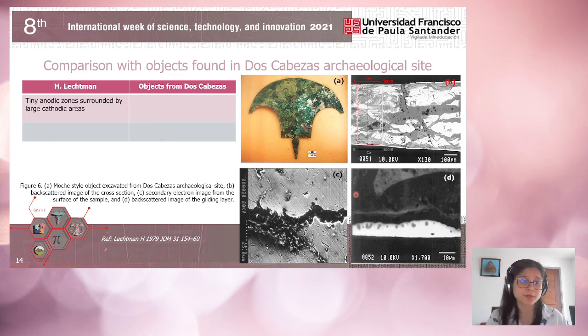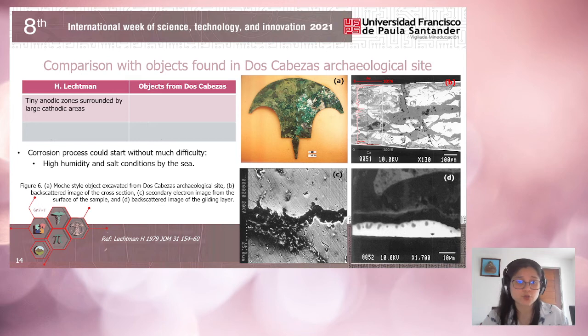Heather Lechtman described tiny anodic zones surrounded by large cathodic areas. This is very curious because that means that the corrosion process could have started without much difficulty at that time, taking into consideration that these cultures developed in the northern coastal region of Peru, where in most of the sites there is a lot of high humidity and salt conditions because of the nearby ocean. Now, this means that perhaps they would have had to re-gild the samples because of the oxide rising.